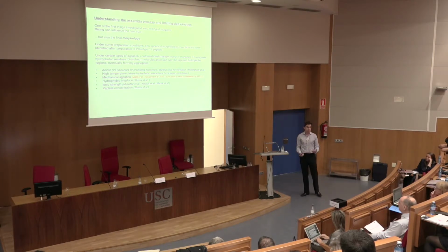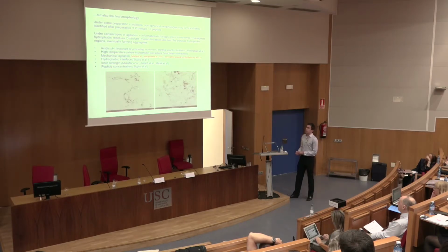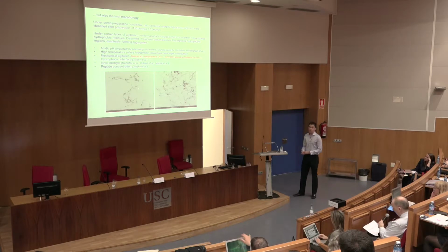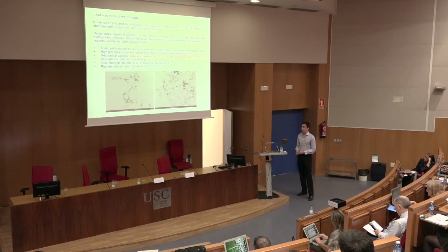Not only can the mixing affect the size, it can also affect the morphology. So under some preparation conditions, non-spherical morphologies can happen. One thing that we were concerned about was fibrillation of insulin, which we hadn't seen much mentioned in the project about this, but we actually directly saw fibrillation in some of our early processes, and we traced it back to a mechanical agitation step, where if you're either vortexing or sonicating your material, you can really encourage other formation pathways, instead of spherical morphologies.